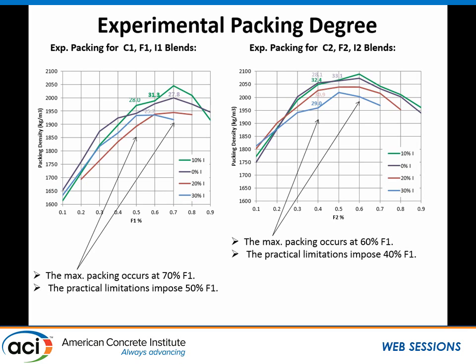So here what you're seeing is, if you plot all these together, the packing density plotted versus fine fraction, you get about 10% higher packing between binary mixtures, which is this purple one with zero intermediate, and 10% intermediate, which is the green one. And you see the same trend in both southern and northern aggregate, but you still see a little bit higher packing in the southern aggregate, which might be due to the fact that it is crushed limestone, which, as Eric mentioned earlier, gives you higher packing, but that might not be beneficial for workability.